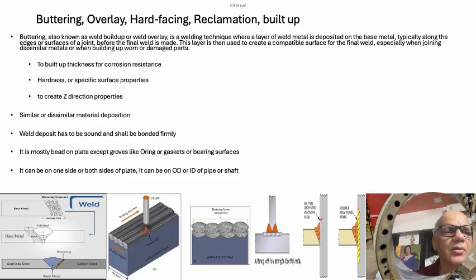And this is, as I said, for building up a thickness which is good to take care of the service life. It may be 1.6 millimeter, 3 millimeter, 5 millimeter, depending upon the service and how aggressive our corrosion is. Sometimes it is used for hardness, that is for hard facing. So like in earth moving equipment, you want a very hard surface which is going to dig into the mud or soil or lift heavy stones, or it can be a part of a crusher, or a part of a shaft where you are going to have the bearing surfaces. So all such areas require a very high hardness, sometimes even crossing 60 HRC, or there could be any specific property you are looking for. Maybe on a hard surface you are looking for a soft surface, or you are looking for creep resistance. So it all depends upon the application.